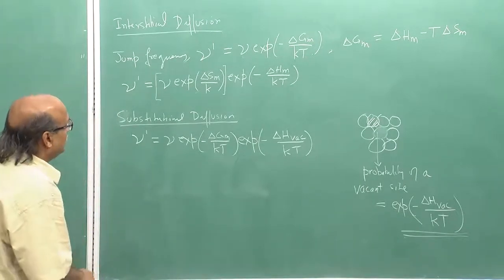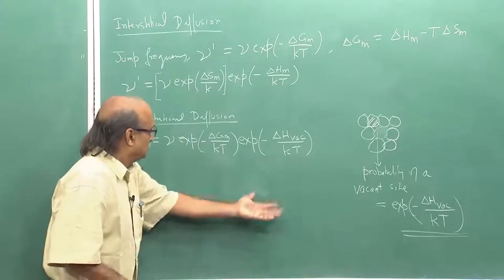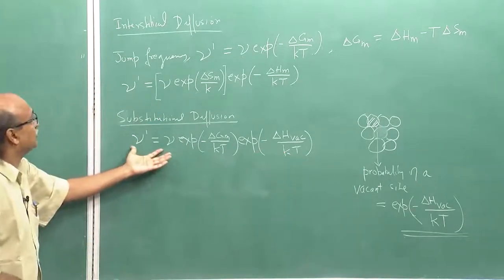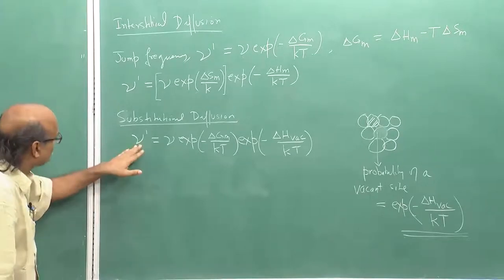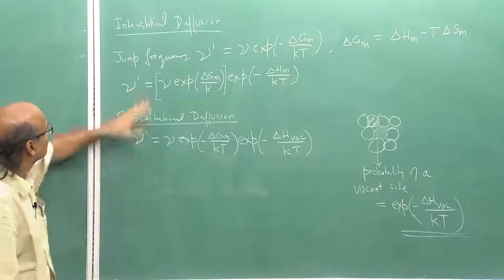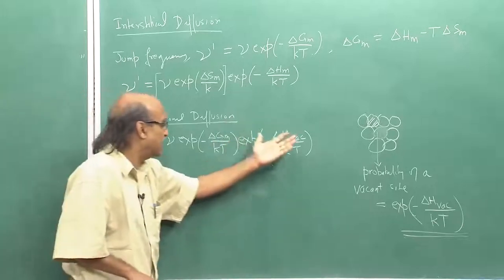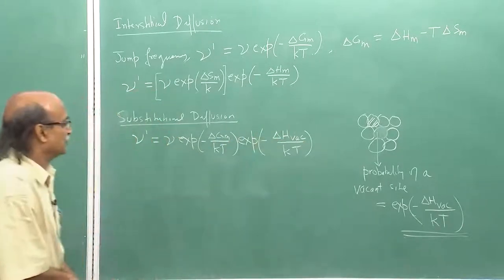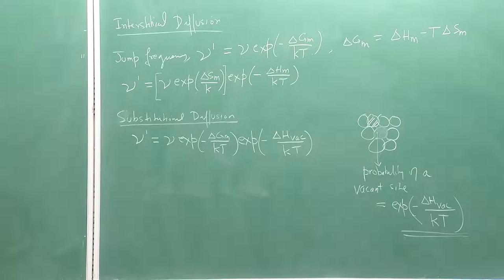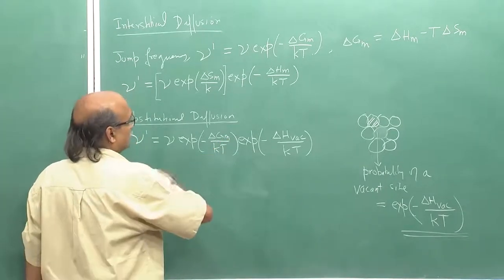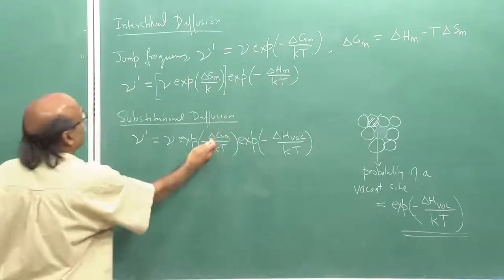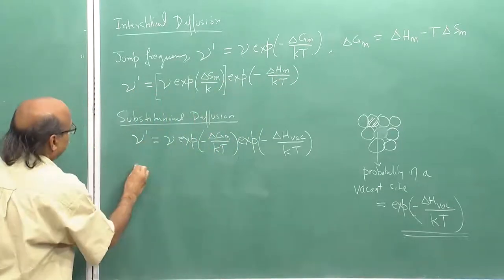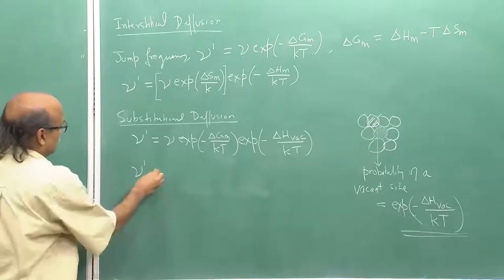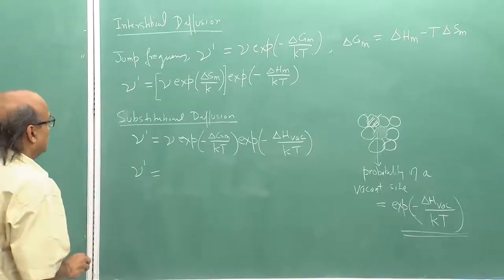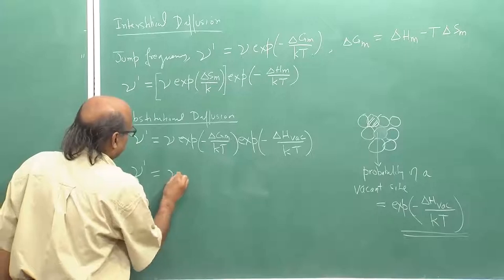So, very clearly, the substitutional diffusion is going to be more difficult, or the jump frequency is going to be less than in the case of interstitial diffusion, because you have an added term which is the probability of a site being vacant. Now, let us substitute for delta Gm in terms of delta Hm and delta Sm as we have done here.